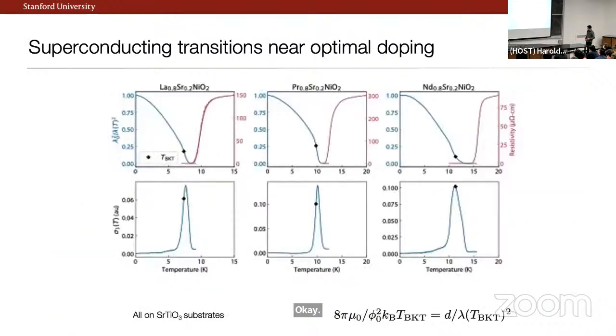So what's the bottom line? Bottom line is, after a lot of work, the basic measurement looks good. The red curve shows when I went to resistance 0, and these blue curves essentially are proportional to that density of superconducting electrons, right? So indeed, where we go to the 0 resistance state, we can see the superfluid electron density come up.